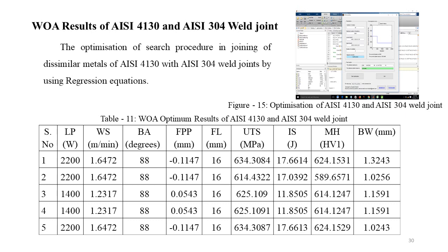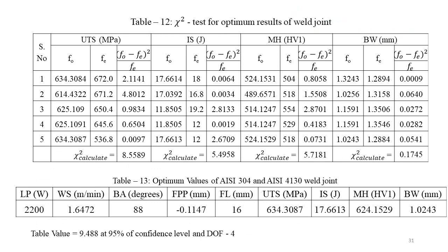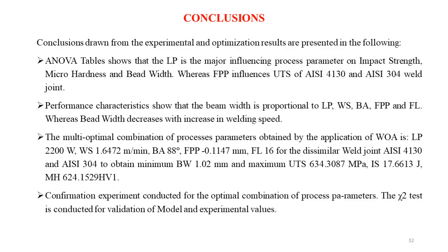For these 5 readings, the experiment is conducted practically once again, and according to the experimental results and optimal results, the chi-square test is conducted. The chi-square tabular value is 9.488, and the calculated value is 8.5589. It is below the tabular value, so the null hypothesis is accepted. Likewise, for bead width, micro hardness, and impact strength, the null hypothesis is accepted.